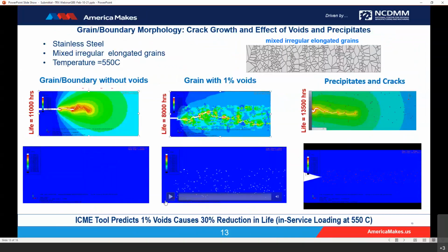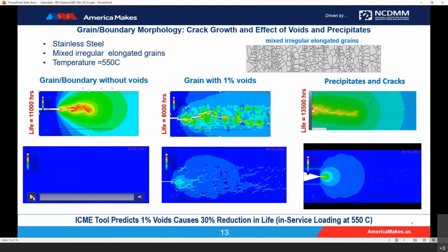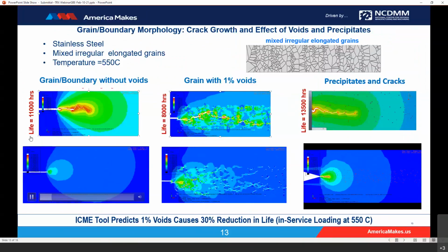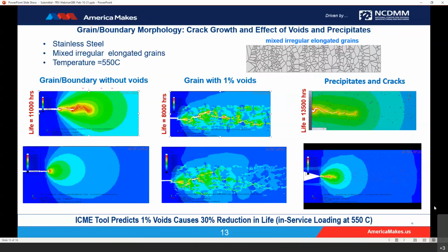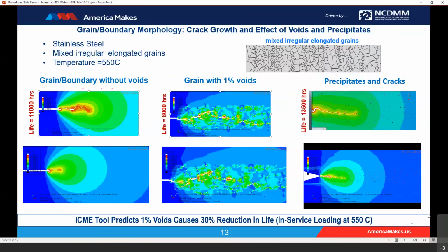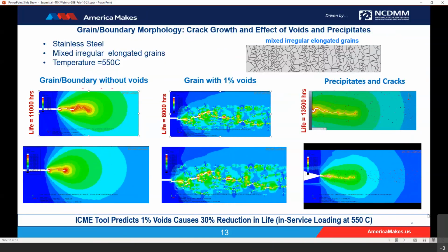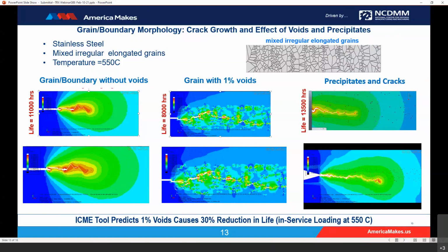So now we're getting to grain boundary morphology and cracks and growth. You're taking that story you saw on the previous slide, and we're applying it to how it impacts overall behavior. In this particular case, we're looking at stainless steel. As you can see on the right-hand side, these are mixed, irregular, and elongated grains at a temperature of 550 degrees Celsius.